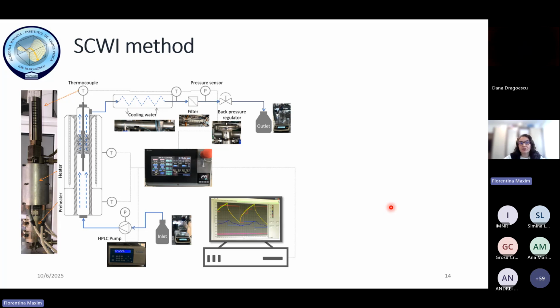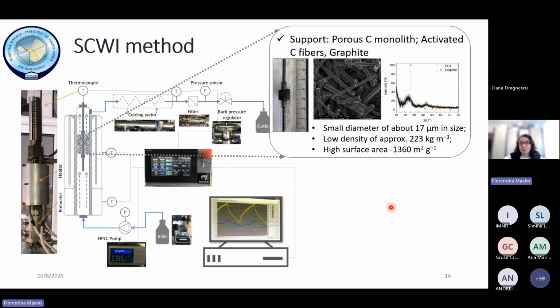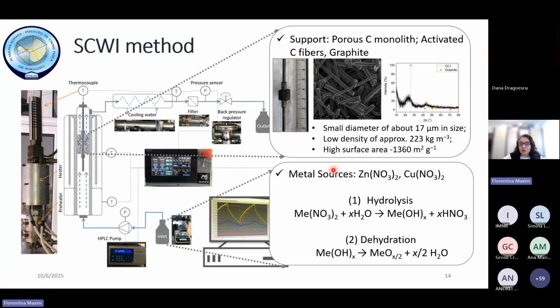Our materials were produced by the supercritical water impregnation method, and so we produce carbon-supported metal oxides by this method. We use as a support a porous carbon monolith made of activated carbon fibers with graphitic structures. So these fibers are quite small. The material is low density, but with a high surface area given by the microporosity within the fibers. As a metallic source, we use mostly nitrates, and I put here the chemical reactions under hydrothermal synthesis. And we study the cases of formation of zinc oxide and copper oxides.